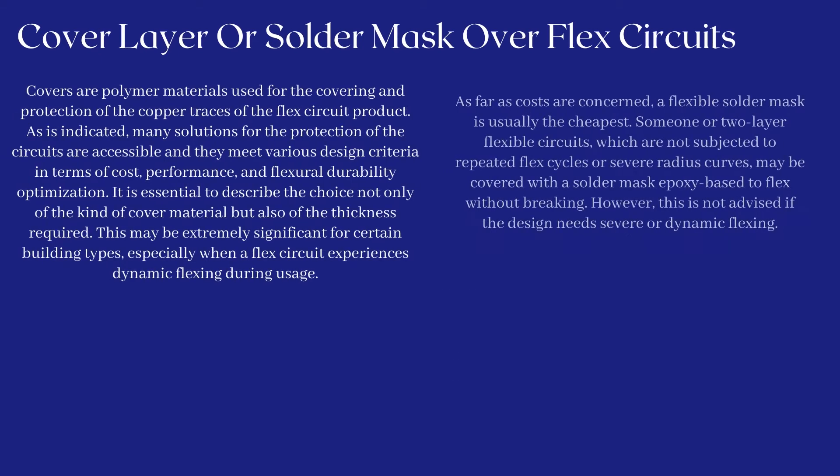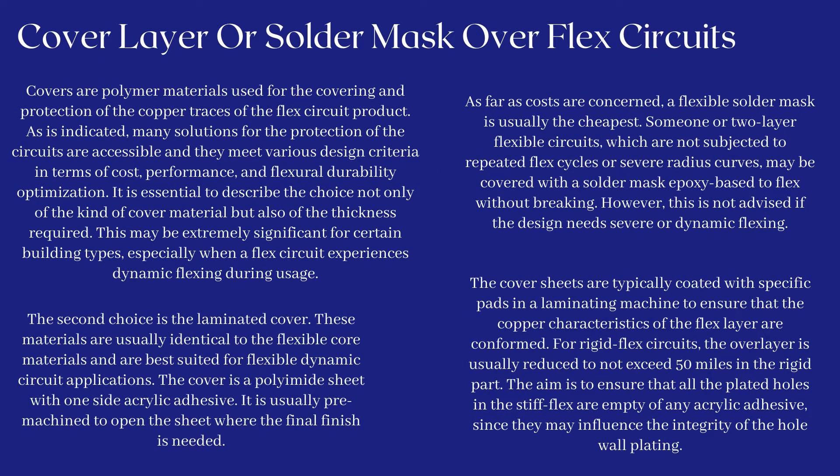Cover layer or solder mask over flex circuits: covers are polymer materials used for the covering and protection of the copper traces of the flex circuit product. Many solutions for the protection of the circuits are accessible and they meet various design criteria in terms of cost, performance, and flexural durability optimization. It is essential to describe the choice not only of the kind of cover material but also the thickness required, especially when a flex circuit experiences dynamic flexing during usage. A flexible solder mask is usually the cheapest option; some one- or two-layer flexible circuits not subjected to repeated flex cycles or severe radius curves may be covered with a solder mask epoxy-based to flex without breaking. However, this is not advised if the design needs severe or dynamic flexing.